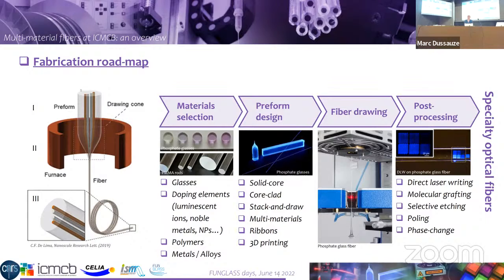The first standard work once we select a material is to verify that this material is suitable for drawing. So we do simple solid core preforms, which are drawn into fibers. But then an important work that we do here is developing regular core-clad preforms and fibers for regular optical property applications. Another thing that we developed recently and worked a lot on is stack and draw revisited. This is the stack and draw that was historically developed for photonic crystal fibers, which we have modified to develop specific ribbon fibers with complex shape.